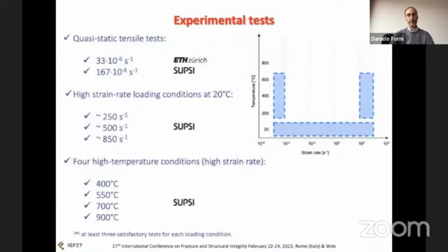And this is the experimental plan we did. Starting from the quasi-static conditions to the high strain rate test at room temperature, then by keeping the same loading condition, we did also the high strain rate test at high temperatures.